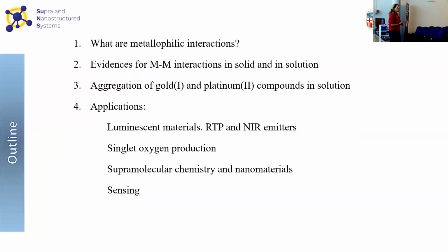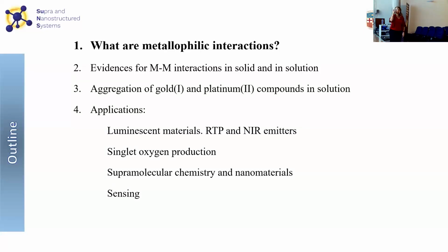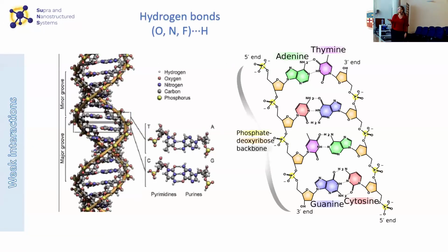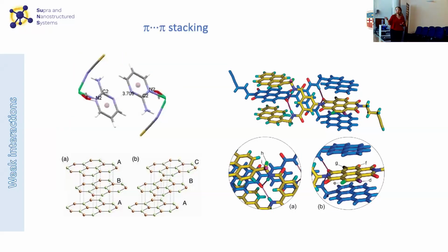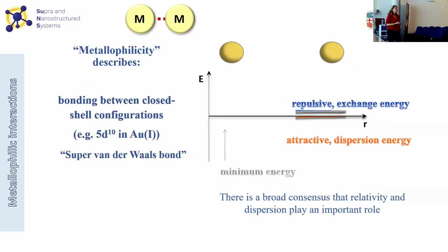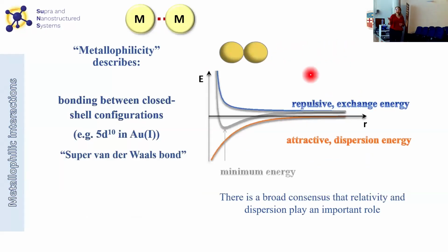First of all, just for those that are not so used to these gold and platinum metal-metal interactions, I would like to show you what these metallophilic interactions are. Okay, so as I said, these normal weak interactions that happen in organic systems, for example, hydrogen bonds, are very well known, mainly those that make the double strand of the DNA. Also, pi-pi interactions are very well known, but what happens with metallophilic interactions? So what we need is two metals that display a closed shell configuration, like gold(I), that is d10. And when they approach each other, they arrive at a moment when they feel better together, let's say, establishing this metallophilic contact that is so strong, more or less with a strength comparable to a hydrogen bond. So this is very important for the resulting properties.